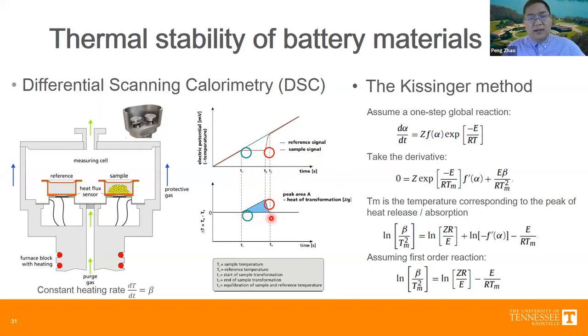A major tool that can be utilized to analyze the DSC results and yield kinetic insights is called the Kissinger method. It's basically, if you consider this process, either endothermic or exothermic, is induced by a chemical process, you can write down this equation easily, where alpha is a normalized chemical reaction progress, f(alpha) containing some reaction order effects, and this is the Arrhenius term, and this is the frequency factor. And by taking the derivative, and also by considering that the temperature rise rate at the peak of the heat release or heat absorption is zero, you can readily come up with the equation.